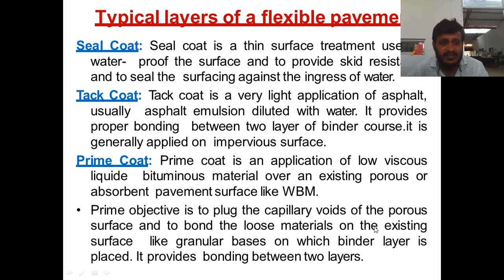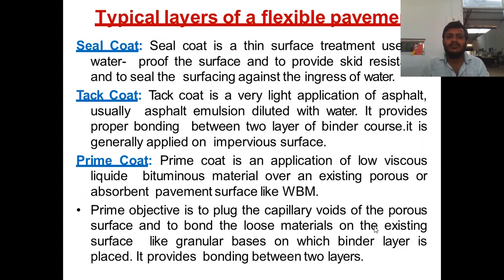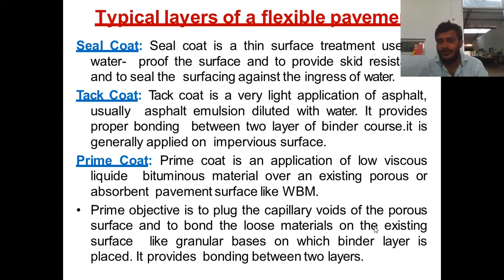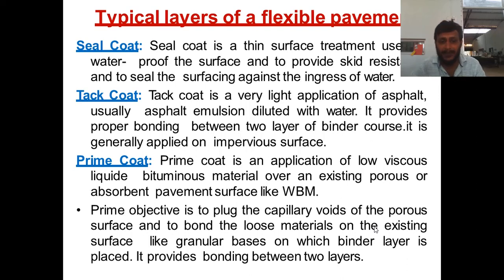Tack coat: provided between the binder course and surface course. It is a very light application of asphalt, usually asphalt emulsion diluted with water. It provides proper bonding between the two layers — binder course and surface course — and is generally applied on impervious surfaces.